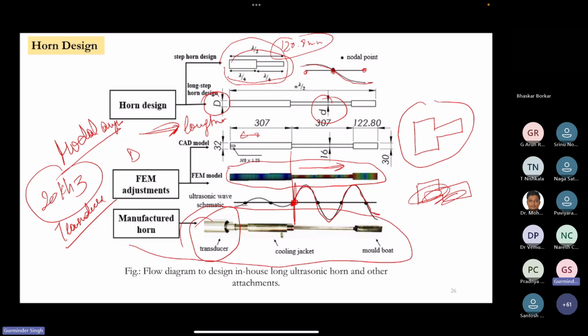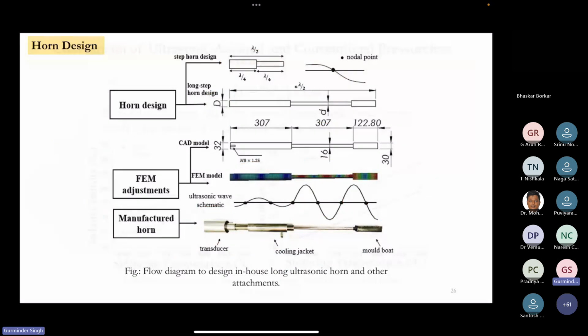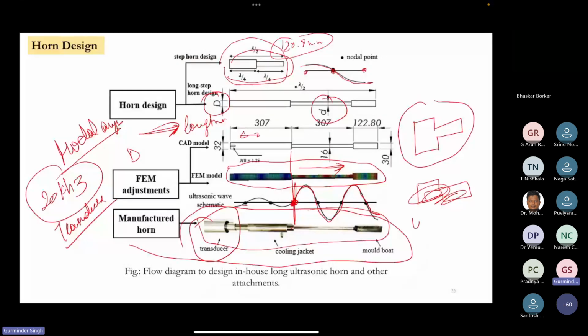After doing this type of FEM adjustment, we came up with the length and the shape of the ultrasonic horn, and we fabricated and tested it with a laser vibrometer, to check the actual natural frequency of this horn, and how much the vibration is amplified when you are giving resonance from the transducer. We were able to amplify from 4 micron to 20 micron, which was enough for these powders, because the powder size was less than 20 micron.